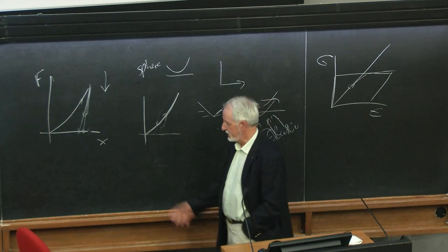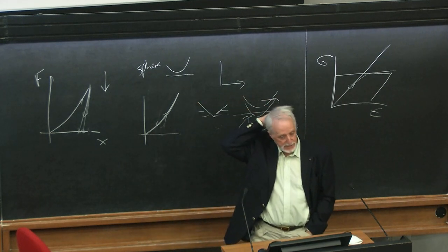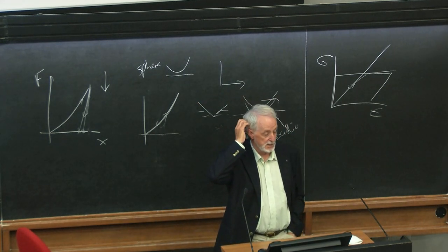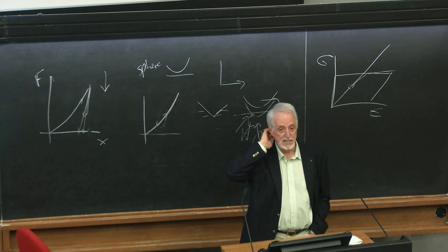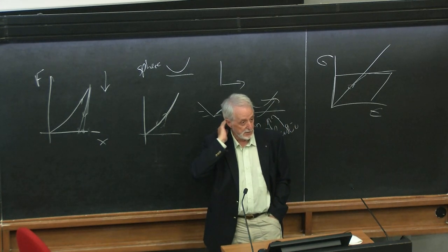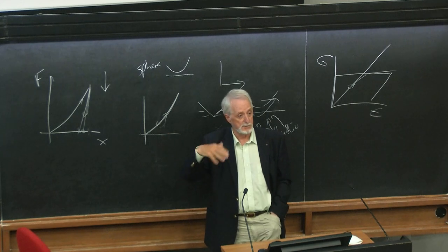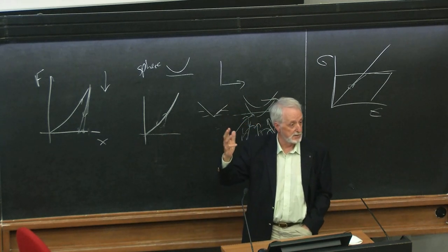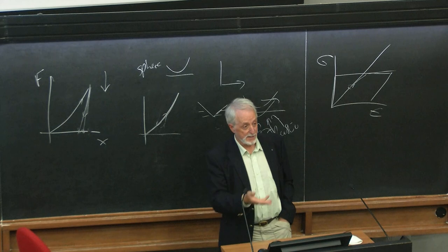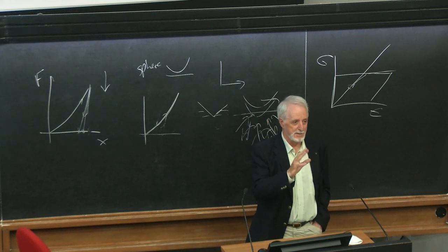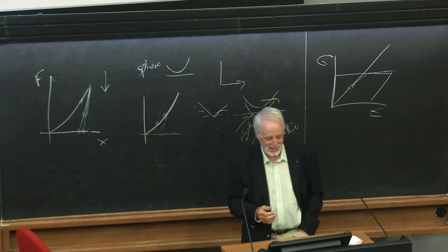Essentially, with these plastic dents, you can quite easily get static friction and high kinetic friction, which is useful, and it's essentially associated with the fact you've made a plastic indentation. You don't require any special magic chemistry or time evolution of anything to do that. You can just get it straight. It's probably why they have hard additives in car tires. I'm not sure about that, but there's that sort of thing.